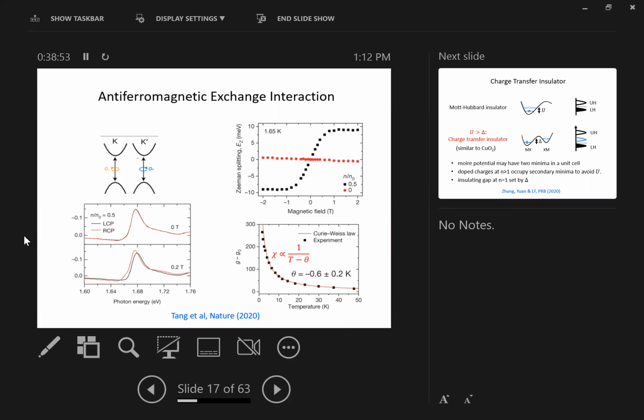Then the magnetization saturates. So there's a sharp rise and then towards saturation. If you look at the slope around the zero field, that slope defines the magnetic susceptibility. Plot magnetic susceptibility as a function of temperature. Here you find a very nice Curie-Weiss behavior. Again, this indicates the presence of local magnetic moments.